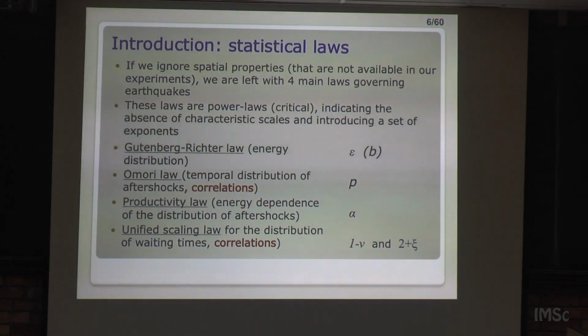These four laws somehow contain some evidence of criticality because they are power laws. And when you have a power law, it means that you have something which has no typical scale. Okay? And when you have a power law, they introduce an exponent that characterizes the decrease of the power law. The Gutenberg-Richter law, that has to do with the distribution of energies of the earthquakes, introduces an exponent that the geophysicists call B, but you can translate it to an exponent epsilon for the energy. The Omori law is related to the temporal distribution, to the existence of aftershocks, the fact that earthquakes are not Poissonian, and measures the correlation of earthquakes, and also introduces an exponent that is called the Omori exponent P. Productivity law is a little bit the connection between energy and time. When you have a big earthquake, then you have more aftershocks. And this introduces an exponent which is alpha.